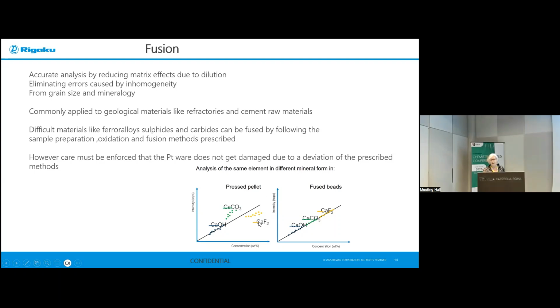To take away the effect of matrix and particle size that is related to pressed powder, we can create the fused bead calibration. And this means now basically all the calcium matrices fit onto one calibration curve. So this is the biggest advantage here. We take away the error related to particle size. We take away the error related to the matrix and the mineralogy.